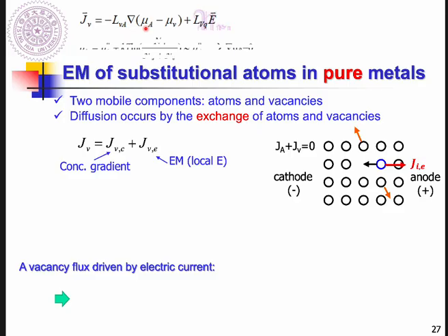As long as you just have two components, to know the chemical potential difference in a system with atoms and vacancies, we write down the chemical potential of atom A. In this material system we do have some vacancies inside. After some derivation, we get the chemical potential of atom A: μA0, the chemical potential of atom A in pure A material without vacancy, plus kT log NA, the number of atom A divided by the total number of atoms, including atoms and vacancies.